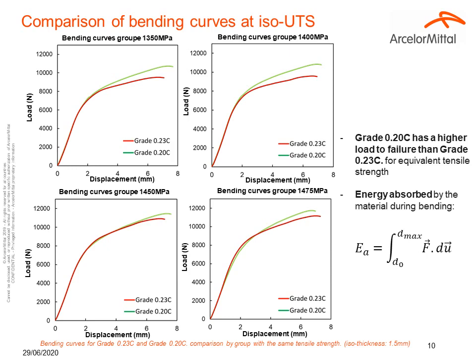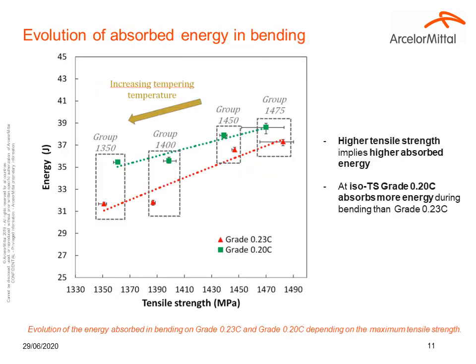This energy can be estimated by the following law applied on a bending curve. During a crash, the material deforms by absorbing energy, and this capacity to absorb energy during a bending test is used as a criterion to compare the two grades. Here is the evolution of the absorbed energy in bending, as a function of the tensile strength for our four different groups.